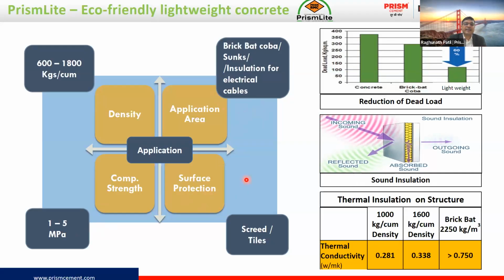A protection layer is required, since the strength is 1 to 5 MPa. So either screed or tiles need to be put over this concrete. For the reduction of dead load, if you compare normal concrete of 2500 kg per meter cube density with 150 mm thickness, the dead load comes around 375 kg per square meter. If we compare the same lightweight concrete with 1000 density and the same thickness, the dead weight is just 150 kg per square meter. So around 60% of dead load is reduced by using this concrete.